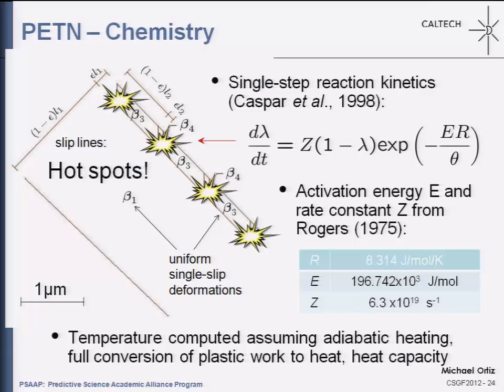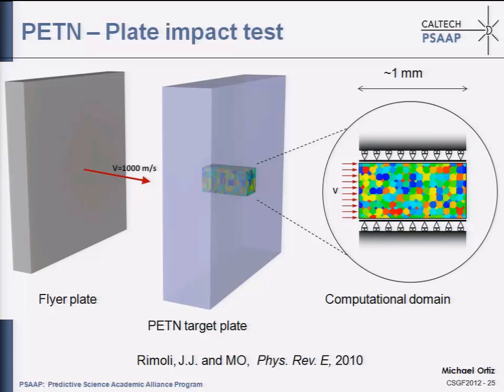So just to demonstrate the connection with chemistry, we used a very simple single-step reaction kinetics as a placeholder to full-scale quantum mechanical chemistry calculations. And so then we try to make contact with engineering testing. So very often these materials are tested in a plate impact configuration. So you have a plate of PETN, and you have a flyer plate that is sent against the specimen maybe at 1,000 meters per second. So that induces a shock that goes through the thickness of the plate, and in some cases induces detonation or initiation. In some cases, it does not.